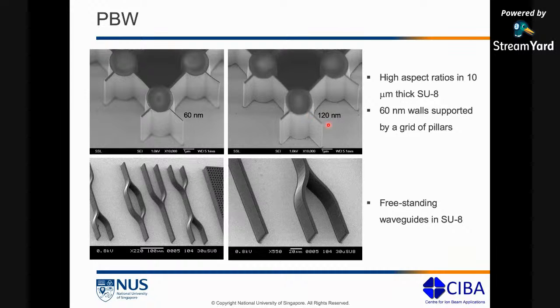Here it's a 120 nanometer, slightly bigger, double this with the same SU8 thickness. Right. So we now use proton beam writing to create these high aspect ratio structures. So here, we have made these waveguides. That's the advantage of using high energy protons for proton beam writing, because protons, depending on the material, have the ability to go fairly deep inside the material with minimum or negligible scattering.